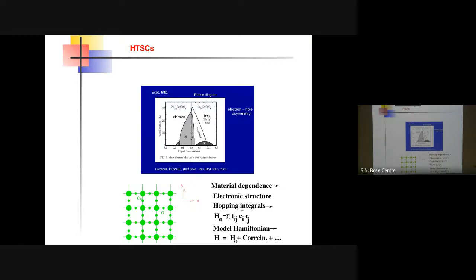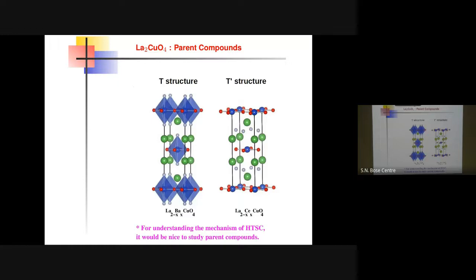But what is interesting is that the maximum point of this dome is called the optimal doping. At the optimal doping, the transition temperature that you get for the lanthanum compound, La2CuO4, is something like 40 Kelvin. But for the same copper oxygen, if you take the mercury compound, mercury barium copper oxide, that temperature is 90 Kelvin. So whatever is causing superconductivity, there is a lot of material dependence. Our goal is to basically get room temperature superconductivity. So for lanthanum it is 40 Kelvin, but for mercury it is more than double. It's 90 Kelvin. So why is that? So before doing that, what we thought of doing is to take the lanthanum copper oxide, La2CuO4.